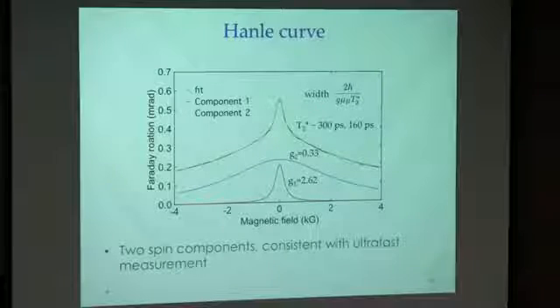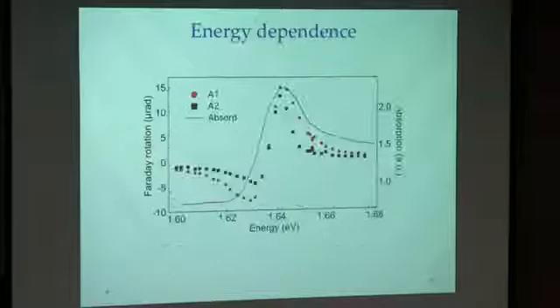Say we assign this narrow peak to the component with the larger G factor, 2.6, and the wider component to the smaller G factor component. And we get lifetimes of hundreds of picoseconds. That's consistent with our ultrafast measurement. So it's all consistent. But what matters here is this energy dependence.